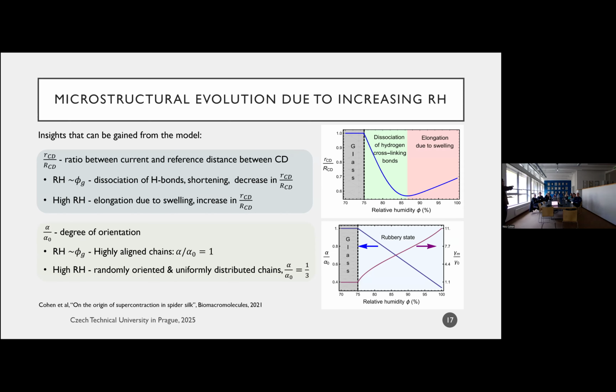Let's see what the end-to-end distance is. Let's see how much it contracts. And so this is one of the simulations that we ran with the model that we had. And what you see is that as long as you're below the critical relative humidity, pretty much nothing happens. Once you pass the critical relative humidity, the distance between the two ends of the chains come closer to each other, right? So the end-to-end distance decreases. And it turns out that a little above 85% relative humidity, the chain starts to stretch a little bit, right? So this was a bit surprising.